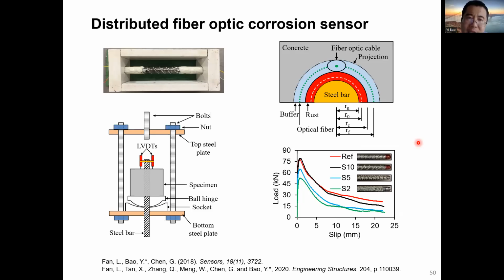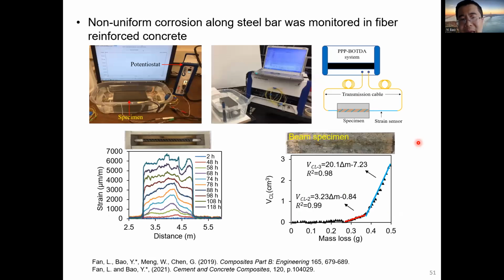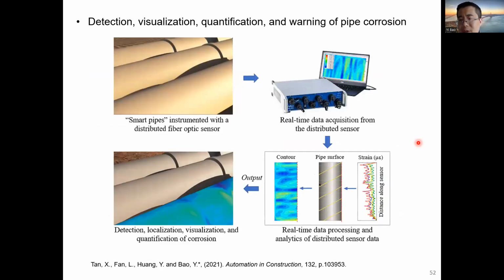And we also evaluated the impact of fiber optic sensors on the interface between steel bar and concrete. So we found that the installation of fiber optic sensor, if the installation is well designed, will not reduce the bond property. And we have applied this technology to several types of materials and structures. So this enabled us to monitor steel corrosion. And in addition to the monitoring of reinforced concrete structures, we also applied this method to monitor the corrosion for pipeline.